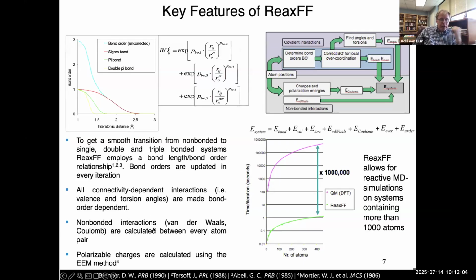Then ReaxFF, as I mentioned in the previous slide, is a second generation reactive force field. So it has a full suite of non-bonded interactions, in particular van der Waals and Coulomb interactions. What is unique to ReaxFF is that they are calculated between every atom pair. So we don't do exclusions. Every atom, even atoms that are sharing a bond, get a van der Waals and Coulomb interaction. Now, for the van der Waals, that's not that important. It doesn't make that much of a difference, but Coulomb interaction is actually pretty relevant.